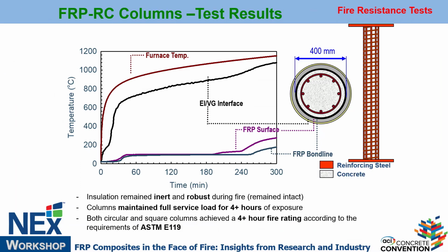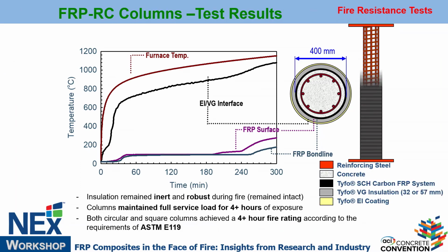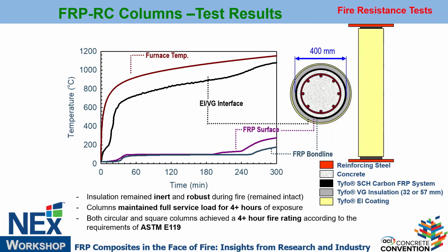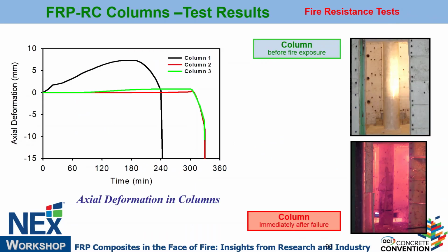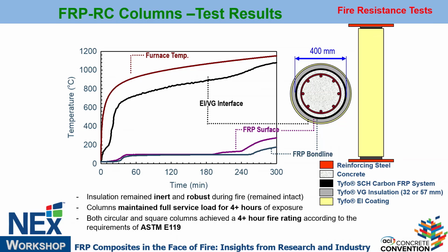Now, just quickly to show, there is a column here, it's strengthened with FRP. This is all supported by industry, so not much money comes in, so they don't want failure. So, quickly we put the insulation as well to make sure it lasts for 3 hours and 4 hours, especially in this project what we did. So, if you see here, this is the fire curve. This is what we have to satisfy, as Steve showed, in ASTM E119. And this is where we put in insulation. This is the insulation temperatures at the edge of the insulation.